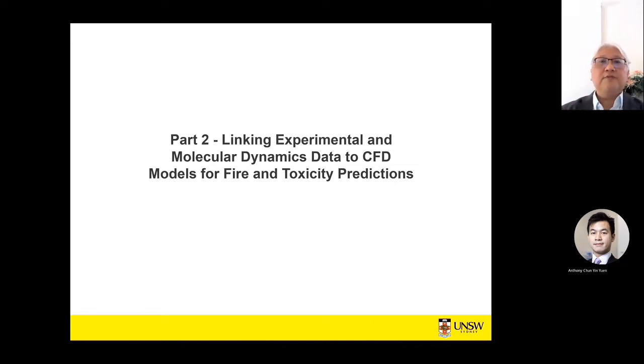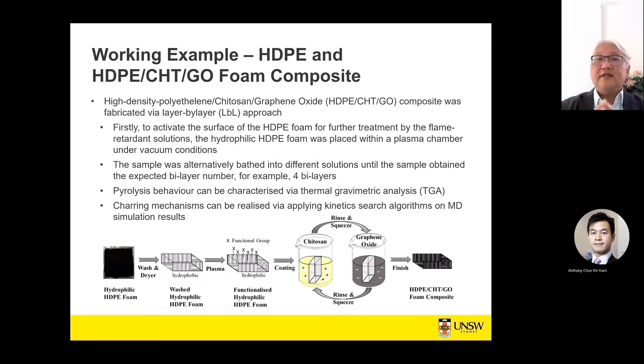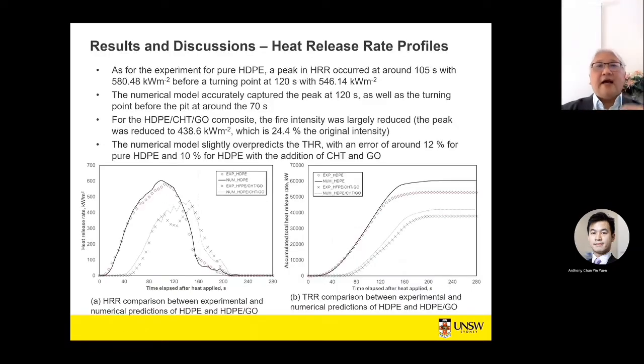Another work we have done is looking at how you link the molecular dynamics data to CFD models. In this work, we took high-density polyethylene and combined it, imagine like a layer-by-layer method, with chitosan and graphene oxide, as demonstrated by this figure here. Based on the high-density polyethylene, we compare with experimental data, and also with the combination of chitosan and graphene oxide. As you can see from this simulation, our simulation data compare very well with experiment. And again, it gives us confidence in how we approach the problem, from the degradation process, and now looking at how flame retardants can inhibit the degradation behavior. Molecular dynamics appears to be able to do so.